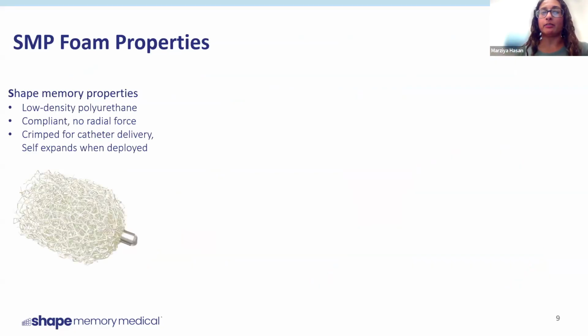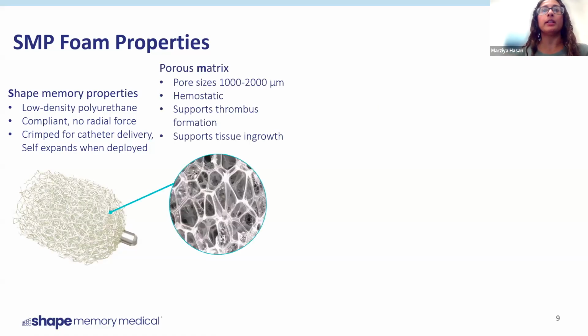Some of the key properties of our devices: we obviously have the shape memory effect that I talked about. Also, because this foam is extremely porous, and we are using a very low density polyurethane composition, there is pretty much no radial force on the vasculature. The shape memory aspect of the device also allows us to deploy this device into various anatomies using a catheter, where it self-expands when it's deployed. The porous structure of the foam is what actually causes clot formation. There's nothing inherent to the material itself that promotes clot formation. It's simply the morphology of the foam, the morphology of the device, that makes it a hemostatic support.